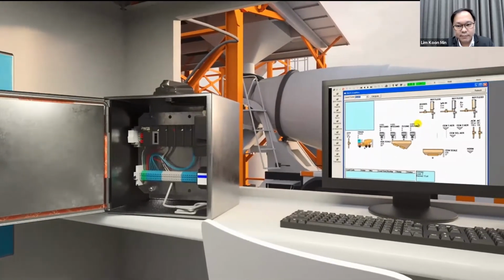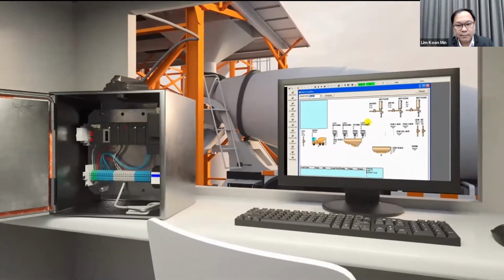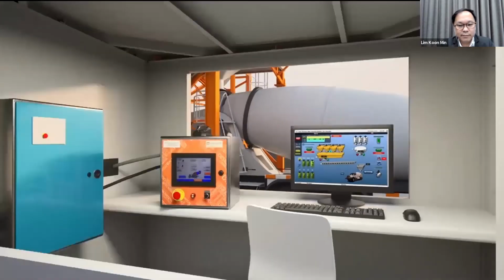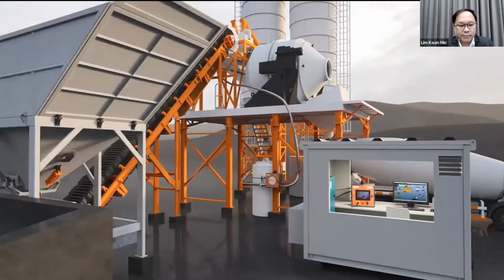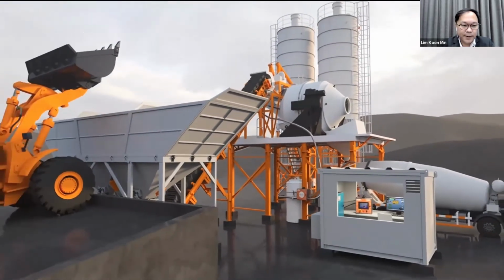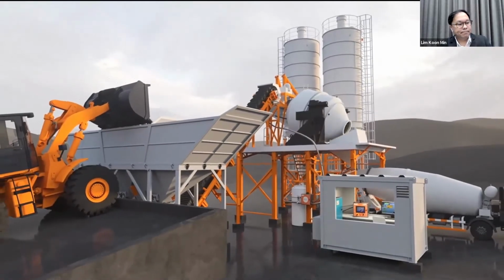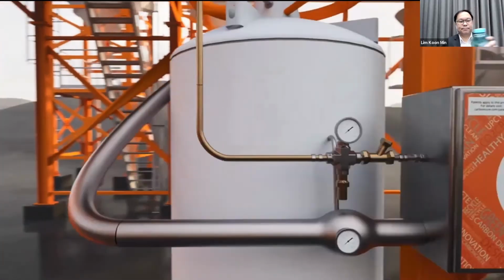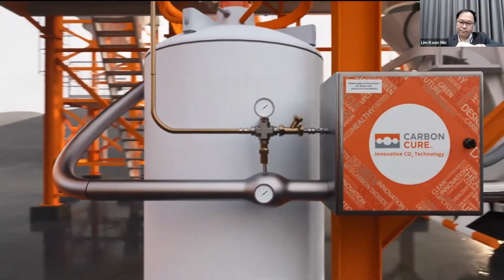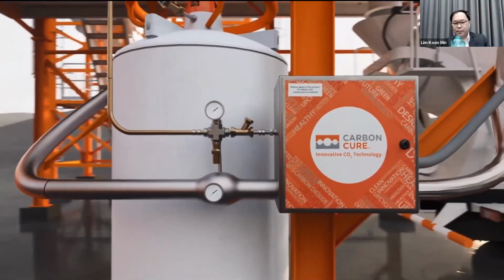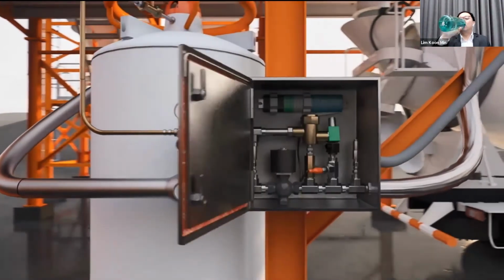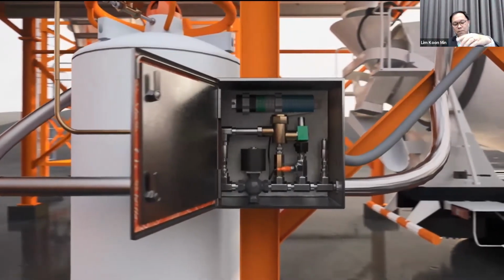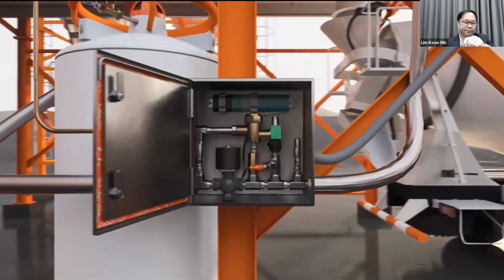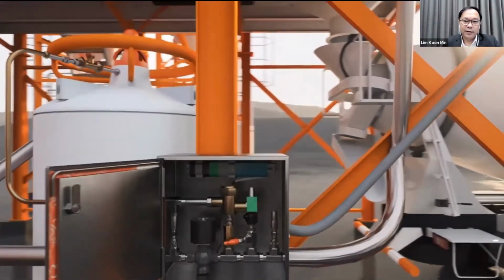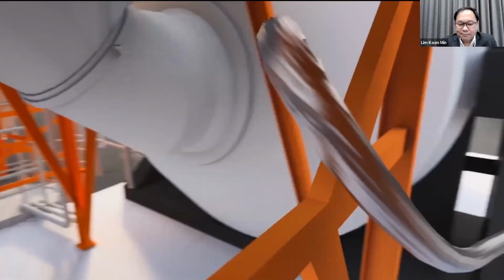The control box software integrates seamlessly with all existing batching software, so adding CO2 into a mix is just like adding an admixture, meaning no impact on batching or loading cycle time. Transfer hoses deliver liquid CO2 from the supply tank to the Carboncure valve box, which is at the plant loading area. The valve box then meters and delivers a known amount of CO2 into the concrete mix based on the cement content of the mix. The CO2 automatically injects into the mix once roughly half the cement and water contents have been discharged.